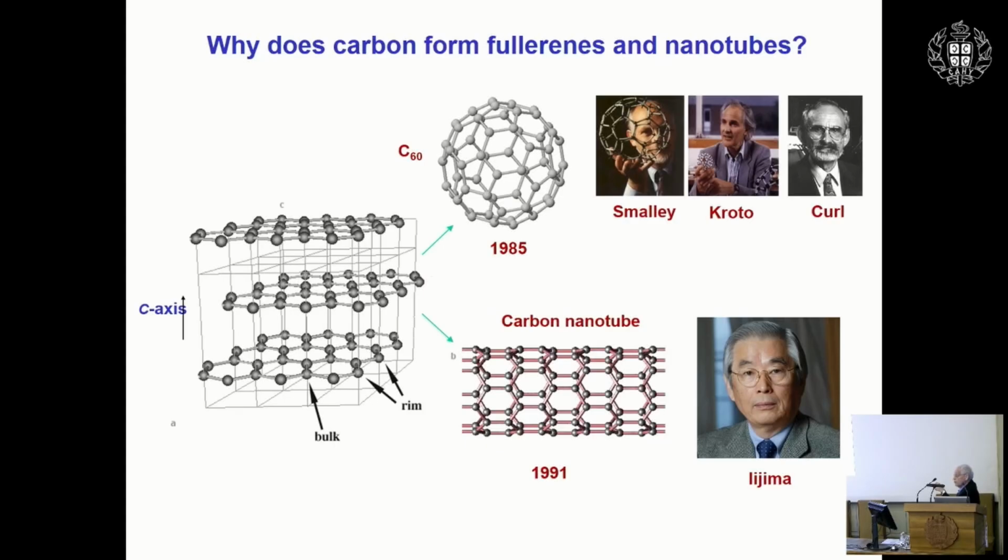He understood that if you bring graphite to the nano size, there are so many dangling bonds on the edges that it will not be stable as flat surfaces, but rather tries to close its structure into a nanotubular structure, or C60 in the case of 0D materials.